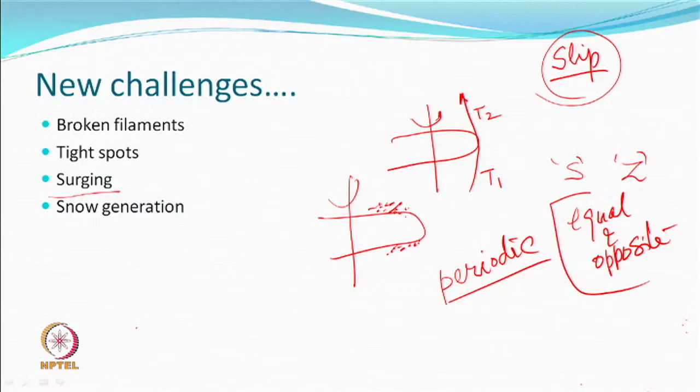And that means you started with a material which had a fixed known coefficient of friction between the surface of the disc and the yarn. And you may end up with another surface which may have a different mu. If you have a different coefficient of friction and you are dependent only on friction for twisting, then you are again getting into a problem. So, you are trying to solve some interesting problem and become smart, and then you keep calculating what exactly is happening.